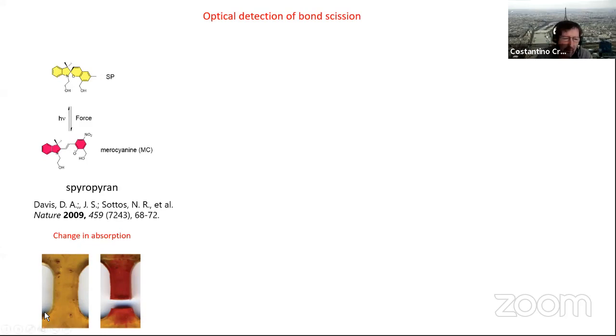So for example, here in the picture, at the bottom, you see a sample. This is from the seminal work of Nancy Sottos and Jeff Moore. They pull on this elastomer sample, and here you can see that it changes color, it becomes red. So in a way, it's possible to detect that.